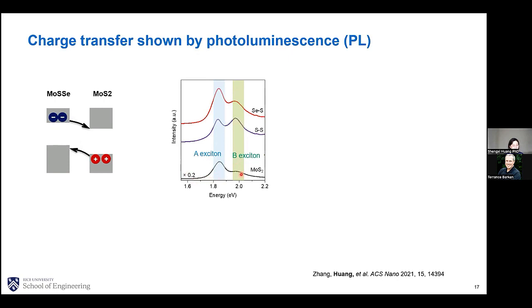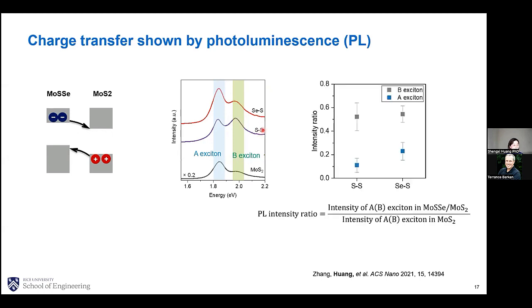Please note here the intensity of monolayer MoS2 should actually be very high because I divided it by 5 for visual effect. Now if I stack another layer of MoSSe here, you can see the A exciton and B exciton intensities are both reduced, but they are reduced differently for different interfaces. So now we can use an equation called the PL intensity ratio. It's defined by the intensity of the A exciton or B exciton in the bilayers compared to the intensity of the same exciton in monolayer MoS2.